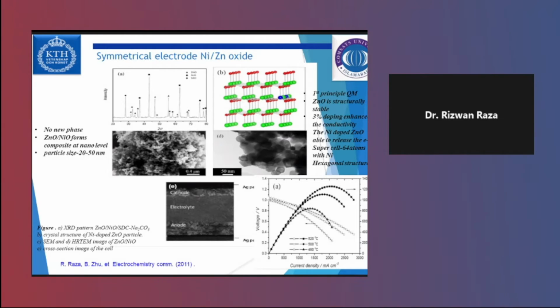the doping of some nickel in the zinc oxide, almost 3%, the electronic conductivity is increased. Actually, in electrolyte there is a need for ionic conductivity, but in anode and cathode there is a need for electronic conductivity, and it has been tested in a fuel cell.